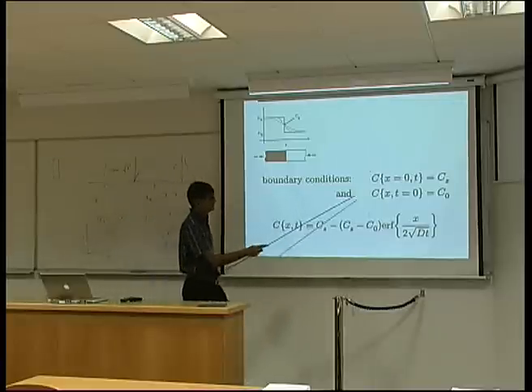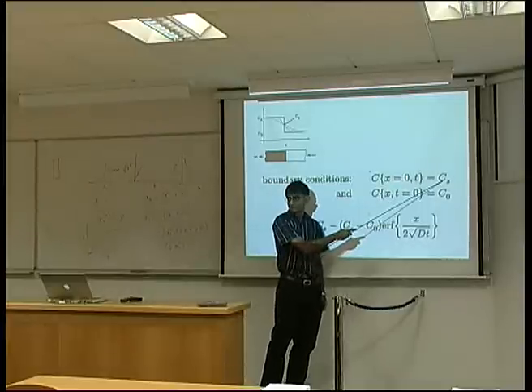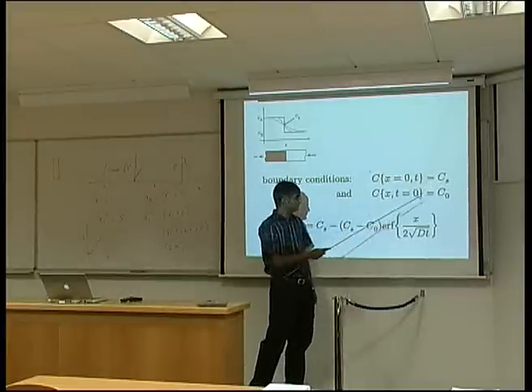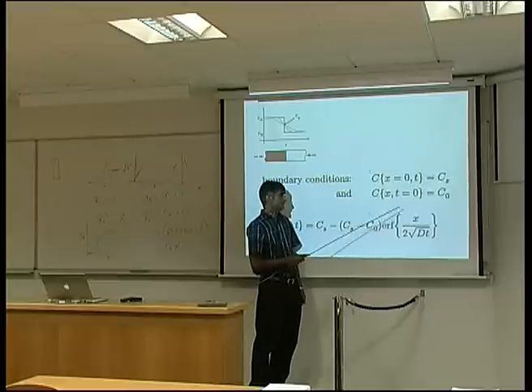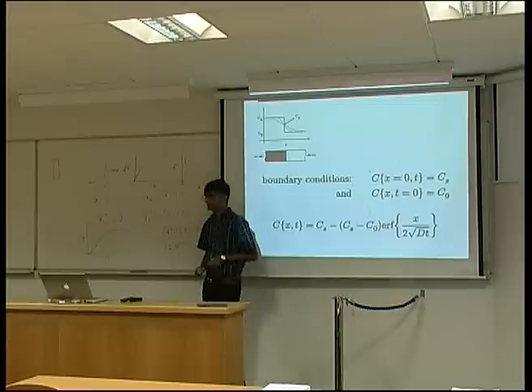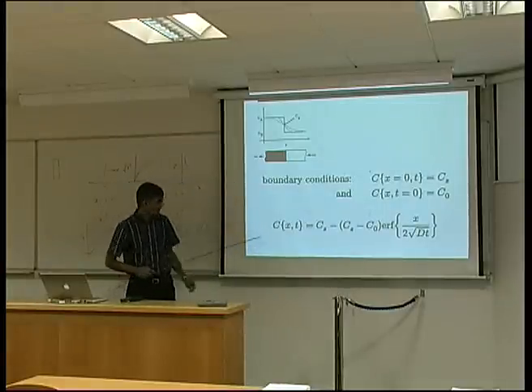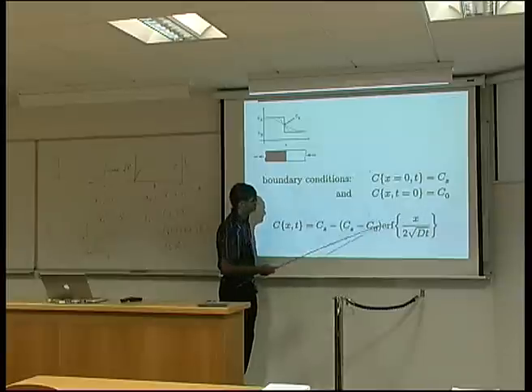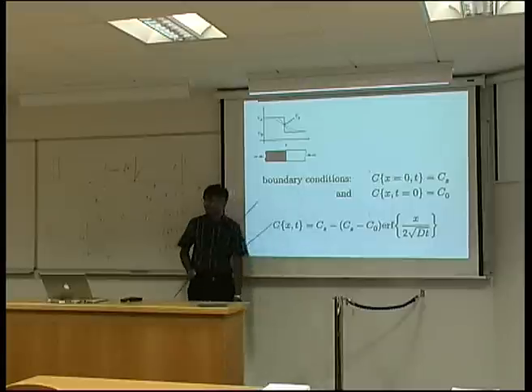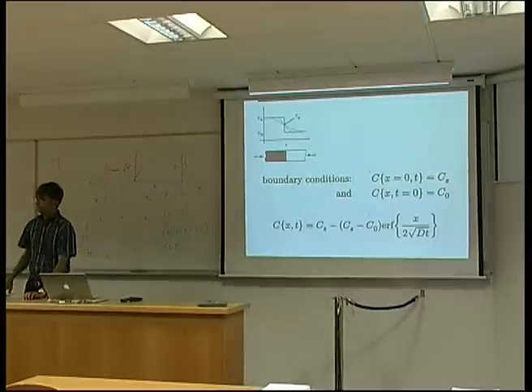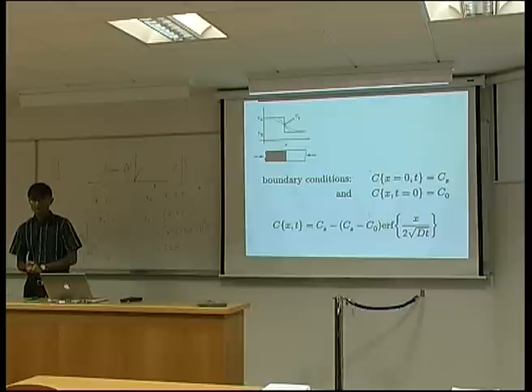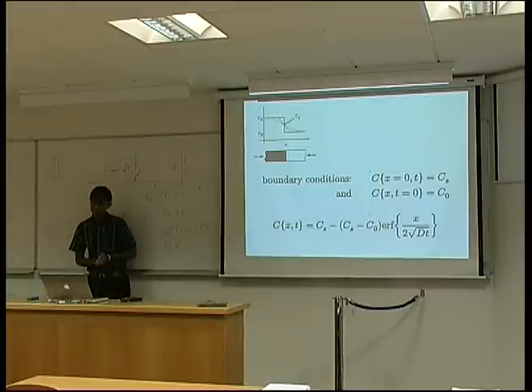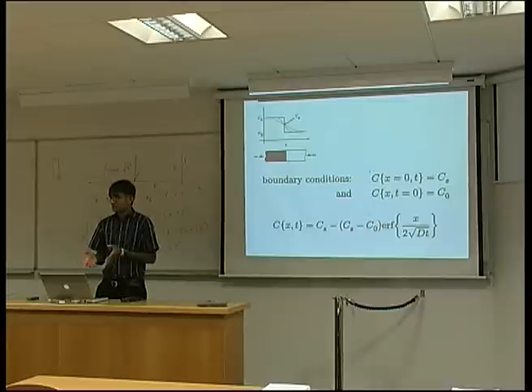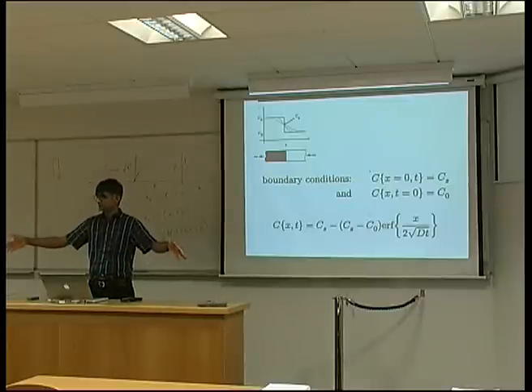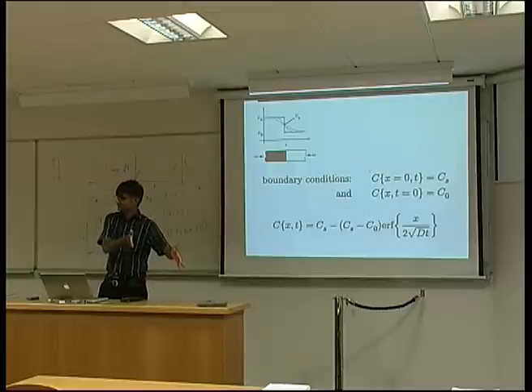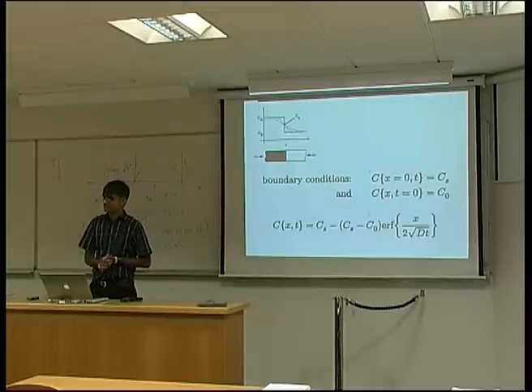And the boundary conditions again are that at the midpoint, irrespective of time, the concentration remains at that mean value, and obviously at x equals 0 and time equals 0, the concentration has a particular value, c naught. And this is how the error function describes the profiles that are described here. Now those are the two key solutions to the diffusion equations, and they describe a huge family of problems. And the meaning of the error function is simply a superposition of a whole series of exponential functions located at different positions. Okay? Everybody happy with that?